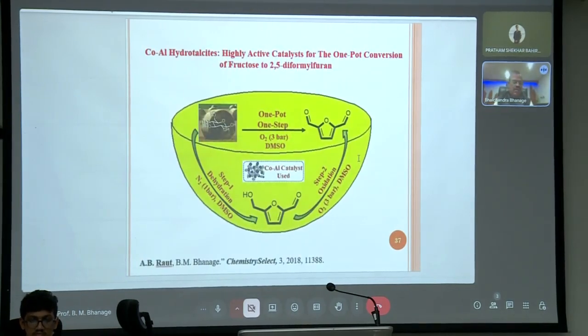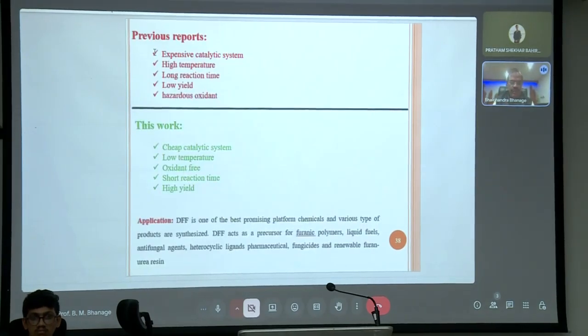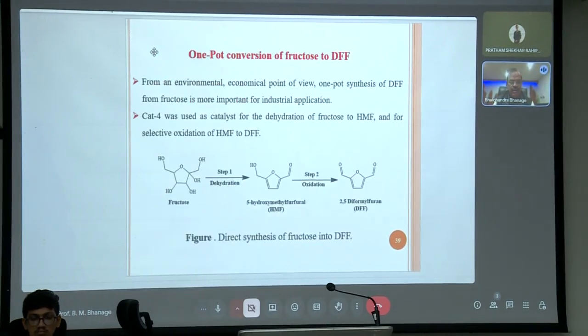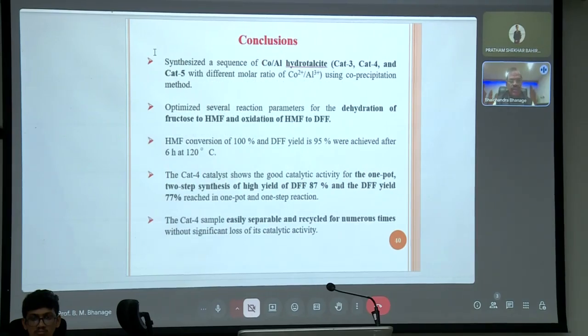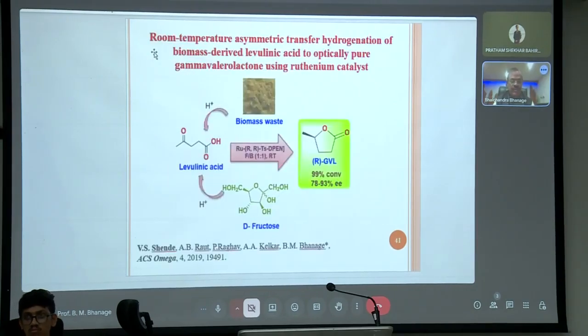Then the question arises whether we can find a replacement for the expensive ruthenium metal. And from that direction we worked, and we found that a cobalt aluminum hydrotalcite catalyst can give you one-pot conversion of fructose to 2,5-diformylfuran. So you can have a good replacement based on the cheaper cobalt aluminum catalyst, which is also stable, robust, and recyclable. So as I told you, DFF finds more application. Here, just by changing the catalyst, we can get similar yields with the cobalt based catalyst.